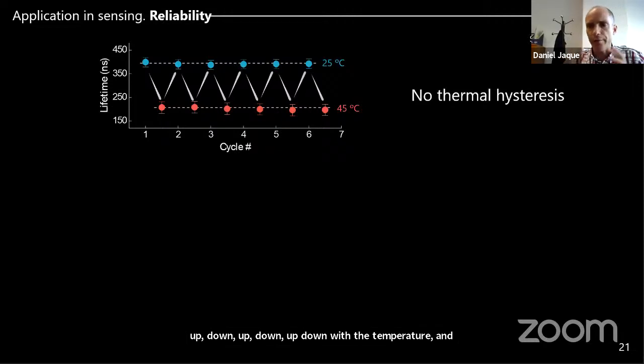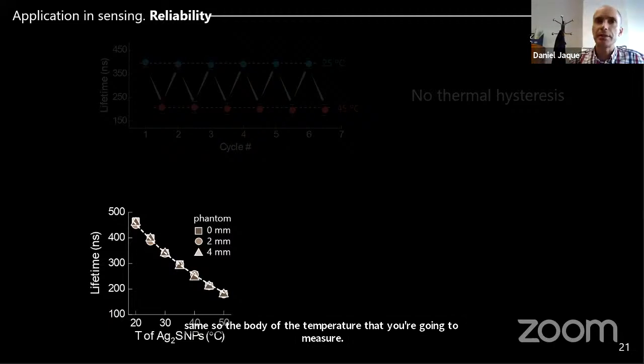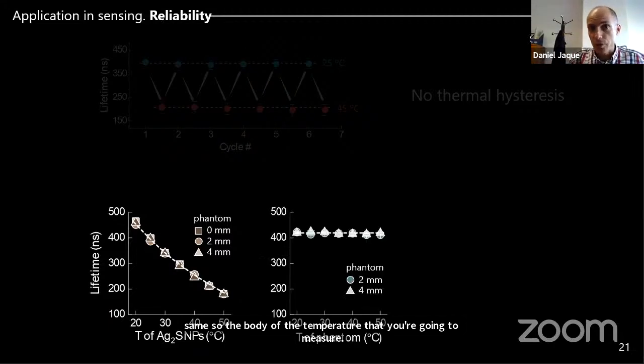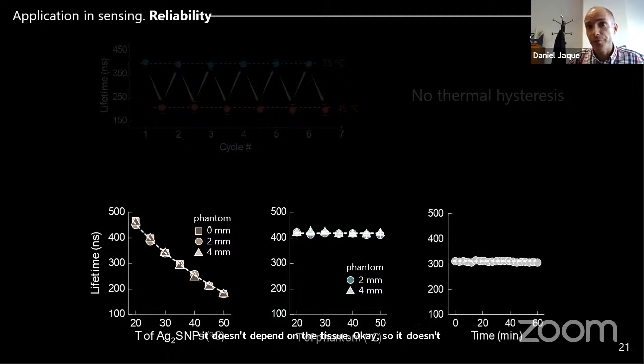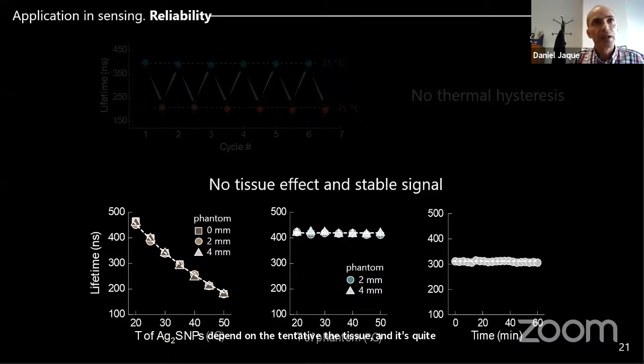So it means that it's a quite robust system, okay? And also it's independent of the tissue. If the nanoparticle is under 2 millimeter tissue and under 4 millimeter tissue, the lifetime is the same. So the value of the temperature that you are going to measure by the lifetime doesn't depend on the tissue, okay? So it's quite stable inside your body, okay?